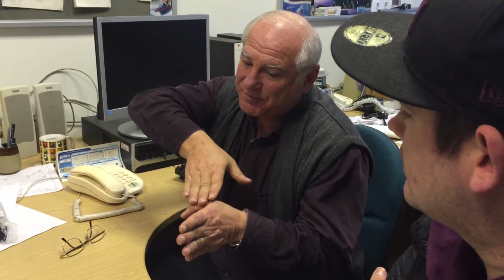And what we have done, we have designed a very special structure in the coating which changes the wear mechanism of the material. So if you think about applying a friction force and then producing a wear particle which is removed from the surface, and if this is your wear mechanism, we have introduced a different type of structure which wears layer by layer by layer by layer, and these layers are on atomic scale, very thin. So that means that you permanently expose fresh surface. So even if your titanium reacts with this atomic layer, you will remove it. And that is the way to eventually tackle this problem. And we have such coatings.